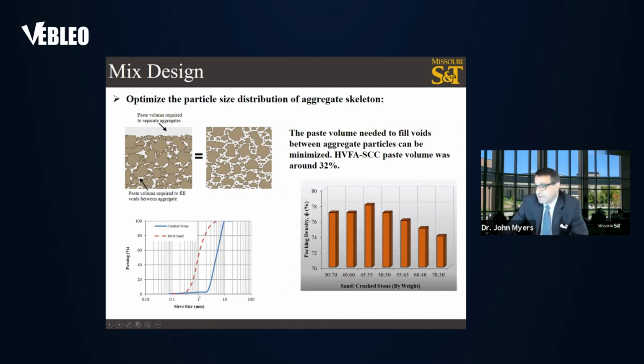In order to do this, we need to know the gradation of all the materials used, in particular, the aggregate sources, including both the fine aggregate as well as the coarse aggregate. And in this figure over here, you can see that in terms of optimization for packing density, a sand to crushed stone ratio of 45 to 55% optimized the packing density for the materials used.